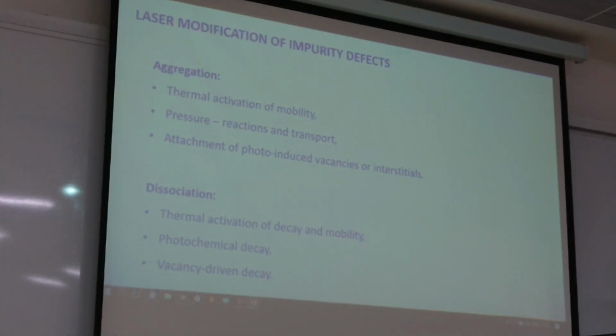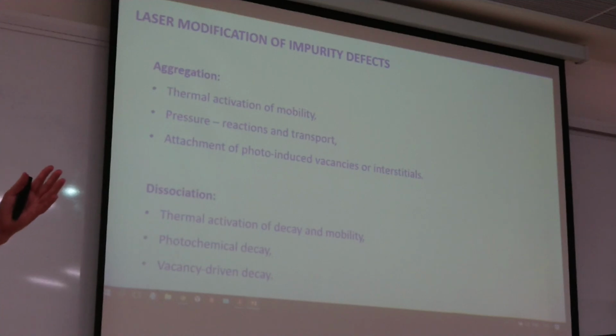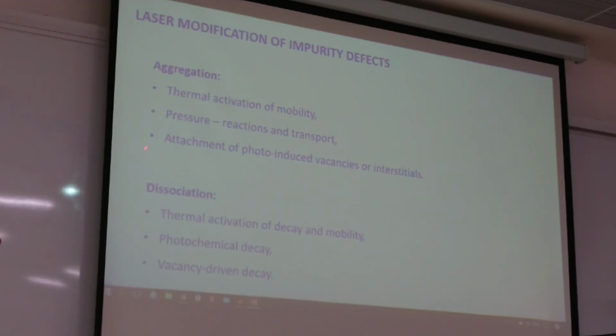If we talk now about laser modification of impurity defects, we can consider two basic processes: aggregation and dissociation. Impurity defects can aggregate if we have laser heating of the material, which activates the mobility of defects, and defects can come together and aggregate, because typically they are stuck and it's difficult to move in the crystalline lattice because of lattice rigidity. Laser can produce local pressure, which induces reactions and transport of defects.